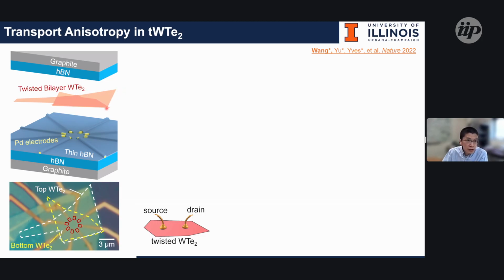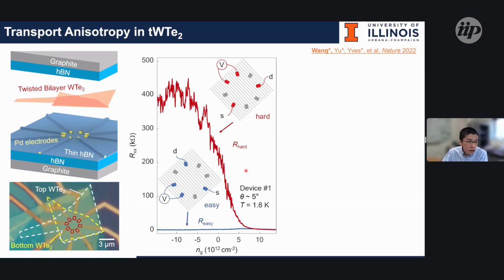So if you have the electrode exposed, you have a high chance of touching the one-dimensional edge of the tungsten ditelluride, which would shorten the measurement and puzzle the results. So what we measure here is that we try to measure the devices along two orientations.